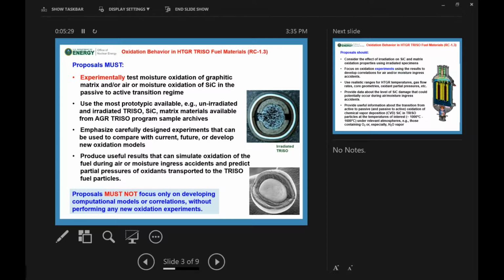The idea here is that we can use these to simulate moisture or air ingress accidents and predict the partial pressures of the oxidants that are transported to the particles themselves. So for instance, if we have a lot of moisture coming in, the graphite blocks could be attacked, which would mean that those compacts, those things that look like the chalk, the size of your finger, that would be attacked, and eventually it could make its way to the silicon carbide. I stress very much that proposals must not be focused on developing computational models only, or correlations with previous results, or doing ab initio, or just sort of chemical equilibrium models. We really want new experiments.